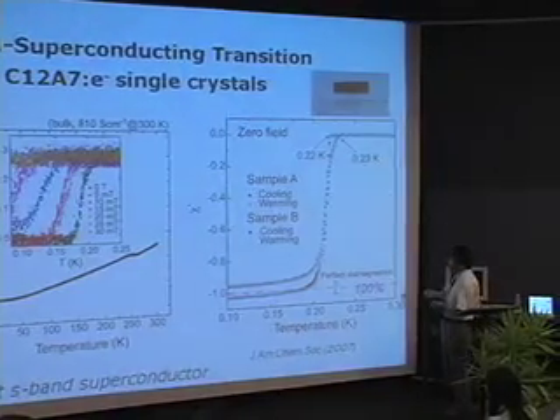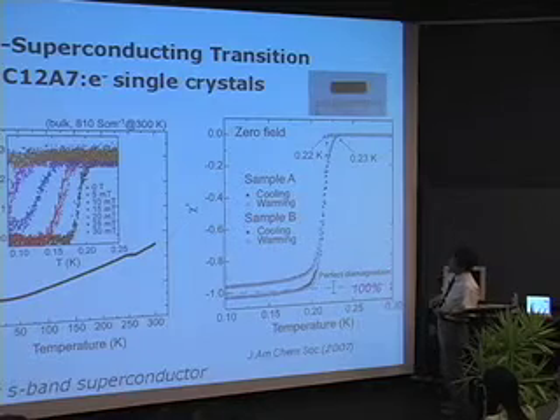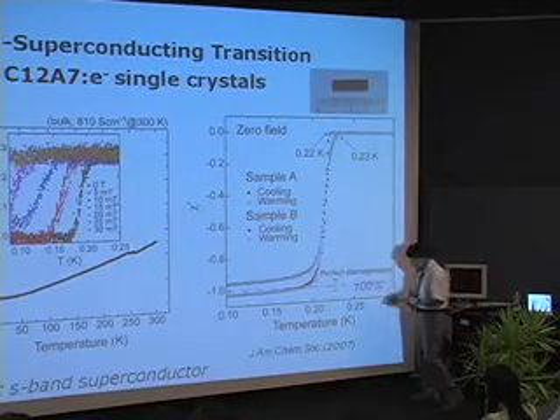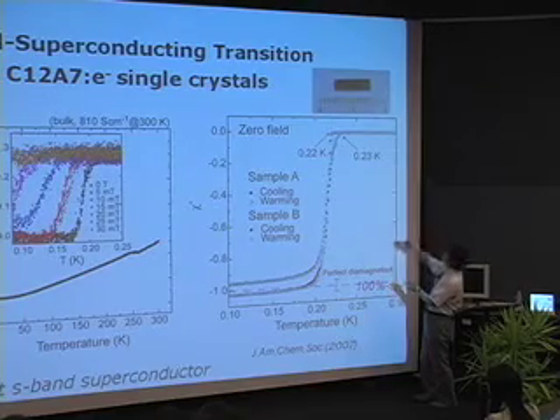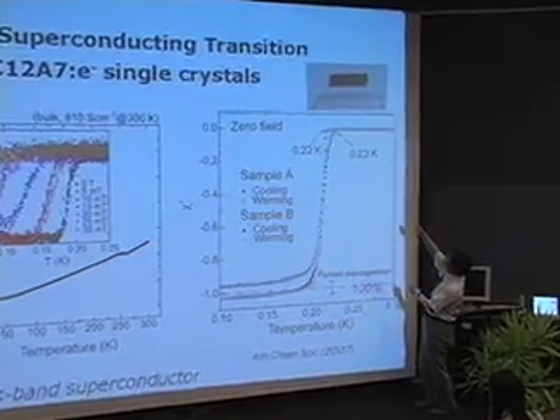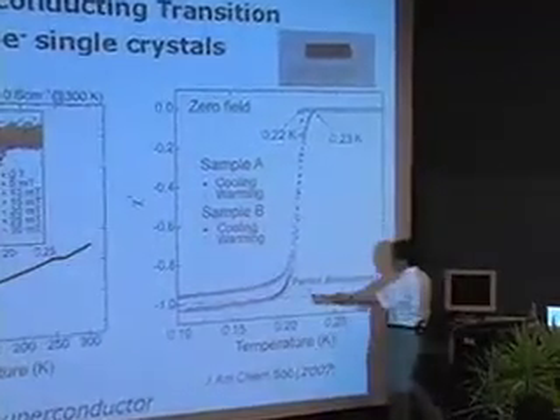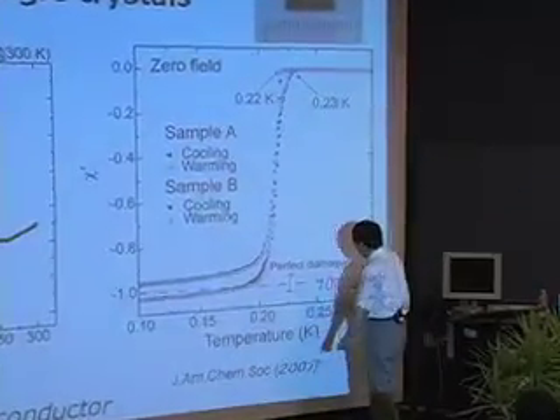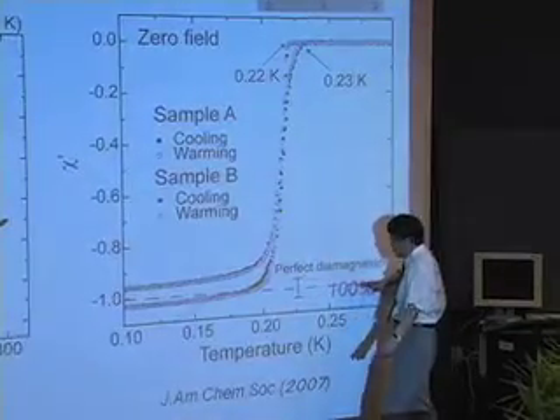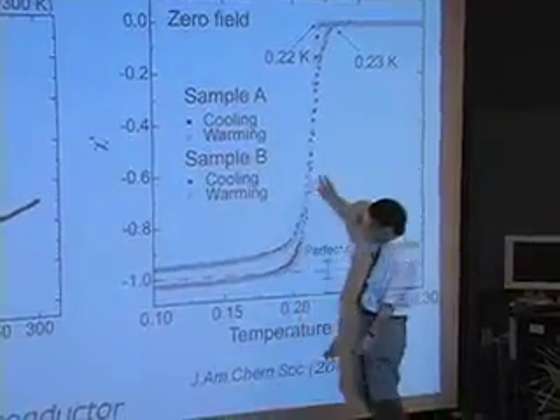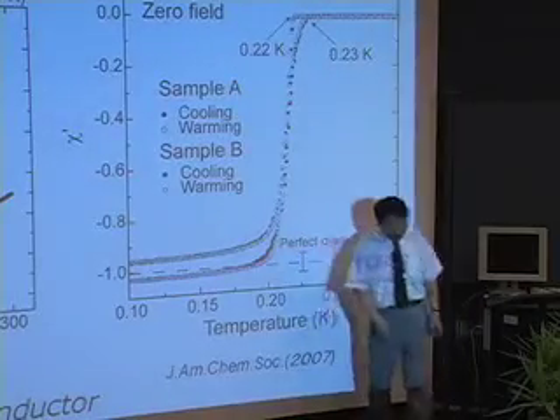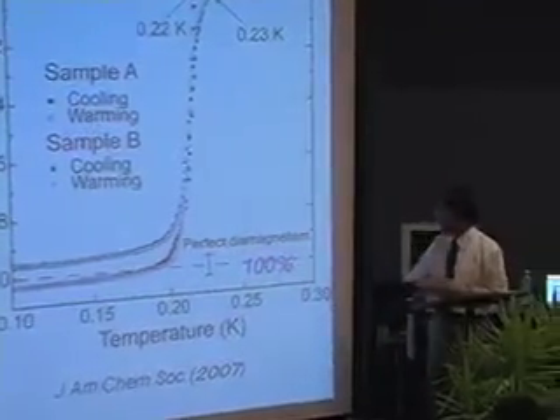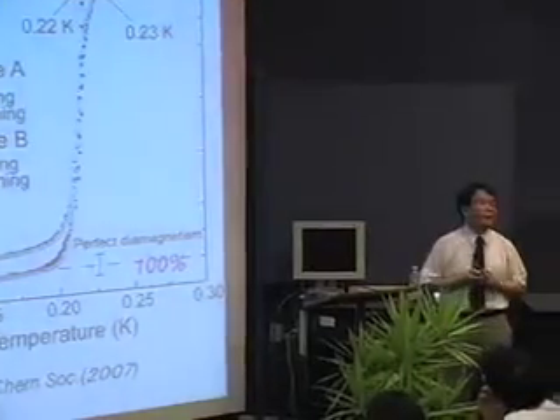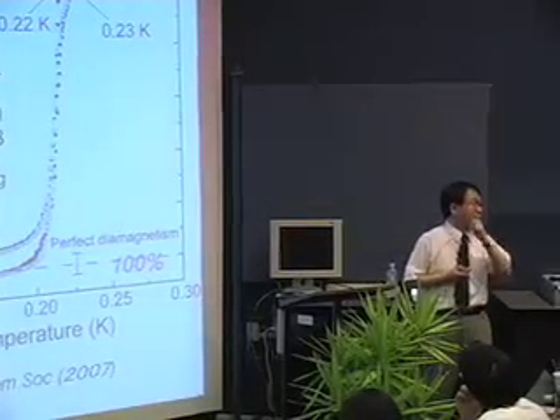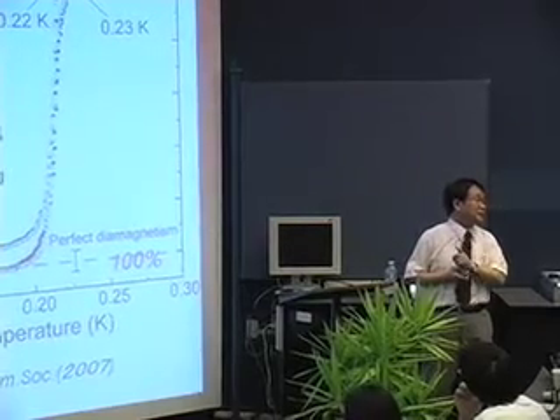This graph shows magnetic susceptibility against temperature. For a whole sample like this, 1 centimeter by 0.5 centimeter, if the whole volume becomes superconducting, chi prime should follow this line. The experimental data is almost close to this line, meaning 100% of the bulk sample converted into a superconductor. This is the evidence of the cement superconductor.